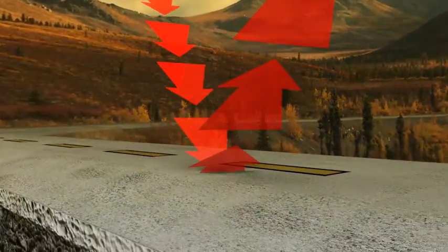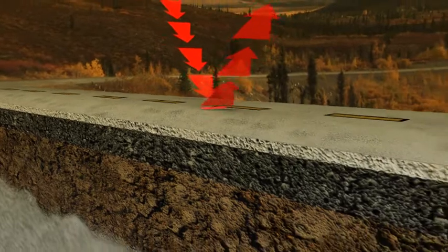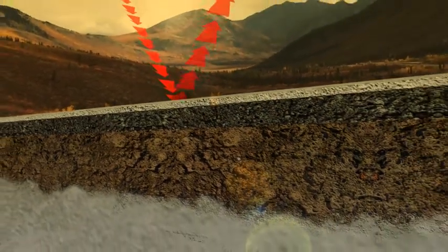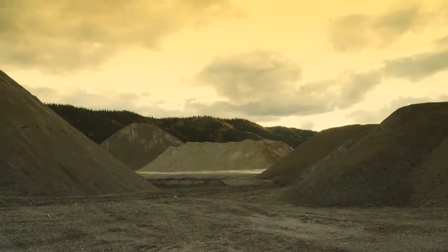An evaluation in Greenland demonstrated that when asphalt is light-colored, the permafrost beneath was found to be intact 1 meter closer to the surface than in areas that were regular black asphalt color. We were familiar with a number of products used to construct light-colored pavements. And we felt that those products could help to solve our problem in Dawson City.